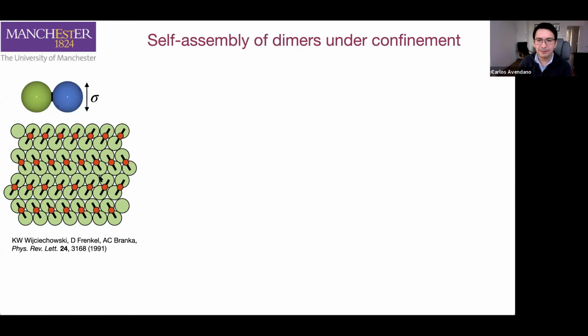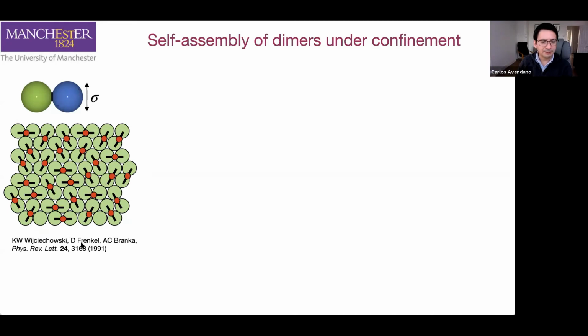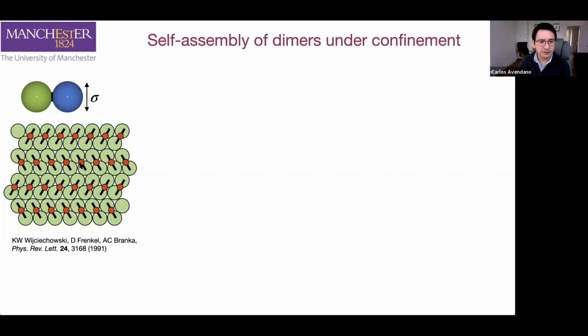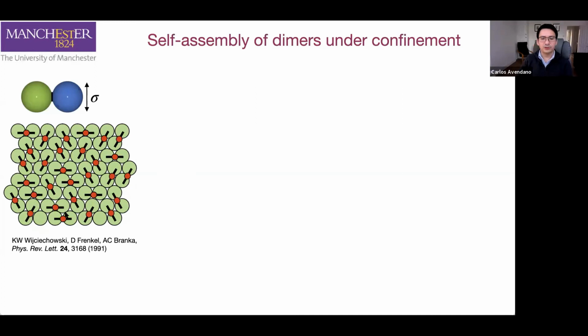It could be in a very well-defined fashion like this, crystal, or it could be completely random. And something that was reported by Daan Frenkel a long time ago is that this second structure is more stable than the previous one. So this is less stable and this is more stable. What he did is very sophisticated free energy calculations, and he observed that the free energy of the two systems is basically the same. But they concluded that this is a more stable structure because the entropy of the orientation of the particles is much higher.